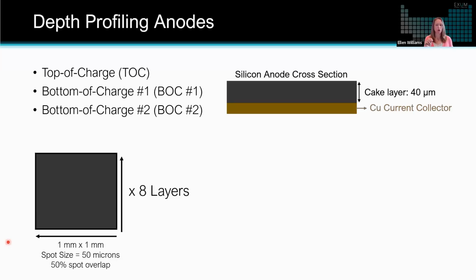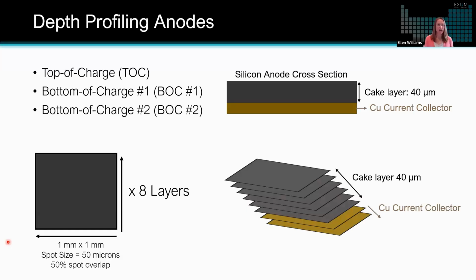But then you can also choose to overlap spots, which allows you to just remove more material per layer. So what we've done in this case is our objective was to try to profile through these 3 silicon anode cross-section samples and see how the lithium was distributed in each of these.